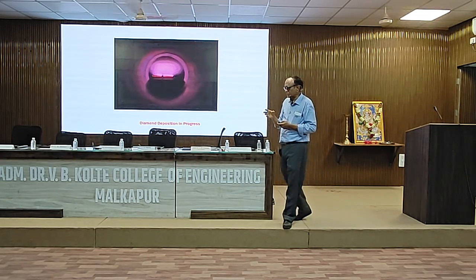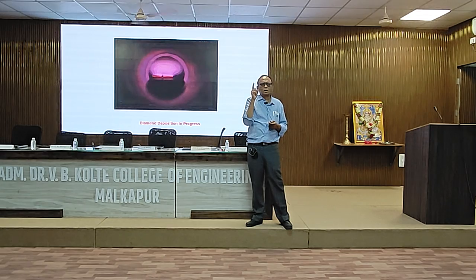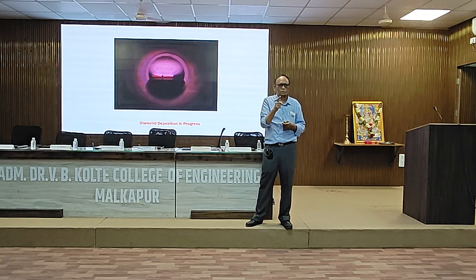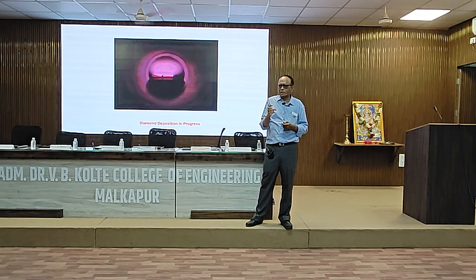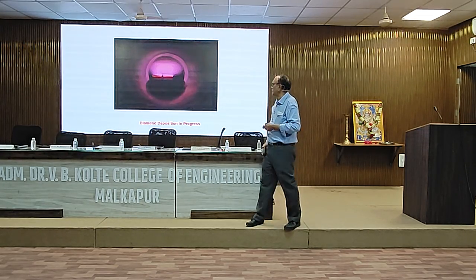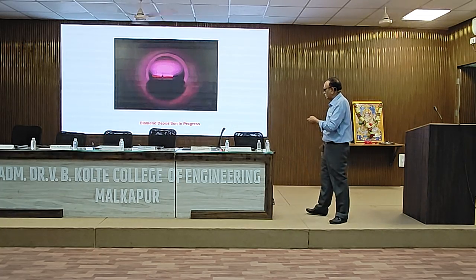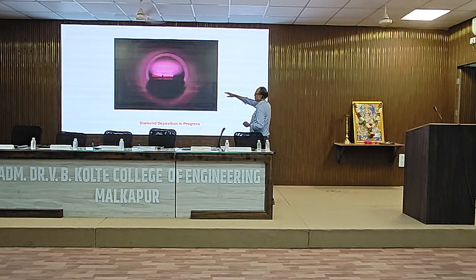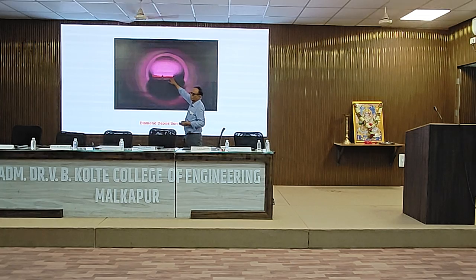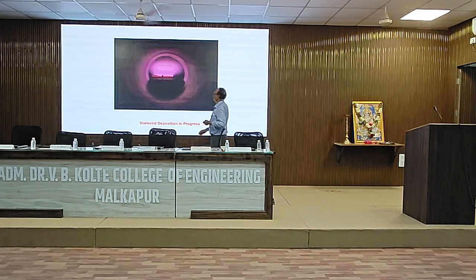And typical composition range is 99% hydrogen, 1% methane. Okay, because you need very high concentration of nascent hydrogen, which will take care of the sp2 carbon, remove that. Basically, it will do the etching of the graphite leaving behind the diamond. And these are the red hot substrates. Again, these are at 900 degrees centigrade. Temperature is again generated by the plasma itself.